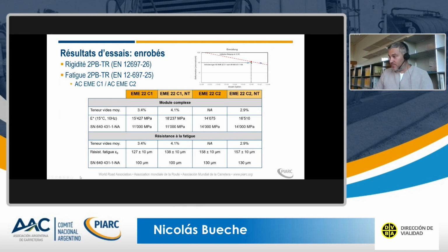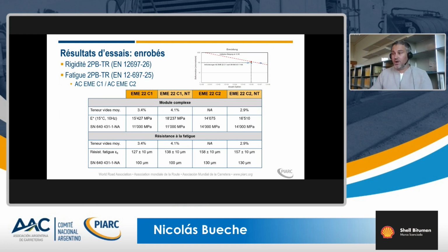And the same for the fatigue, and we are above the limit value of 100 or 130 microdeformation. This means for high modulus asphalt, warm or hot, with a high dosage of reclaimed asphalt, we can meet the target value of stiffness and fatigue test, which for us was quite interesting.